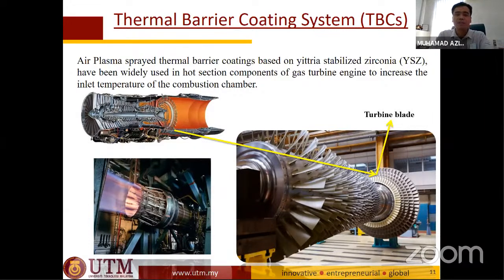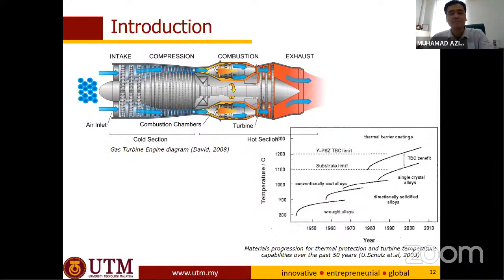So the coating, to increase the performance or the durability of these turbine blades, basically we coat with ceramic. Okay, this is the area I mentioned just now. And this is basically the evolution. For the gas turbine, previously we used wrought alloys. Then they moved to cast alloys. They went for directionally solidified alloys, which basically reduce the effect of creep, as I said just now. And then they moved to single crystal alloys. But because of the high temperature, an oxidation problem will occur. So therefore, there is a need for the thermal barrier coating, which is the ceramic coating.